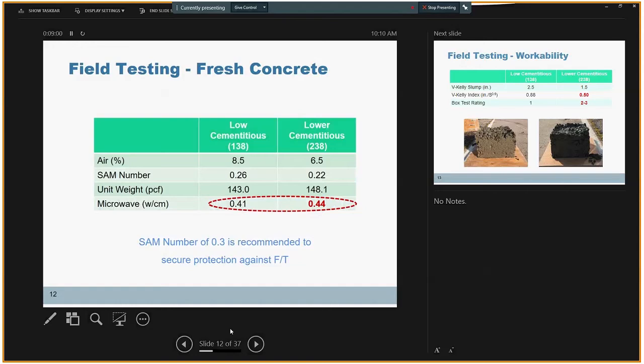The SAM number, or super air meter test, provides a good index of the distribution of air void in fresh concrete. And in order for a concrete to have proper frost durability, we need a SAM number lower than 0.3, which in this case, both concrete mixtures satisfied, exhibiting a proper air void system.